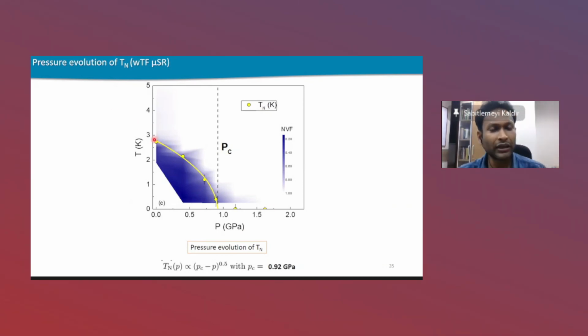Okay, so from the weak transverse field measurements, we have carried out the long range magnetic ordering as a function of pressure, and we have seen that the critical pressure is of the order of 0.92 gigapascal.